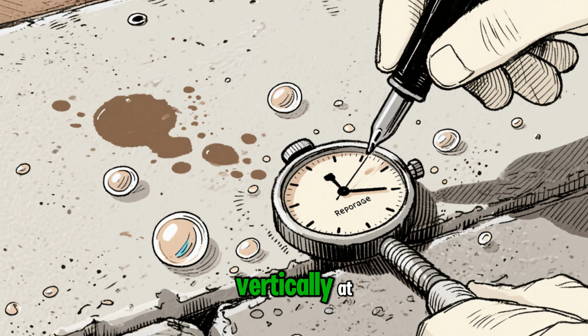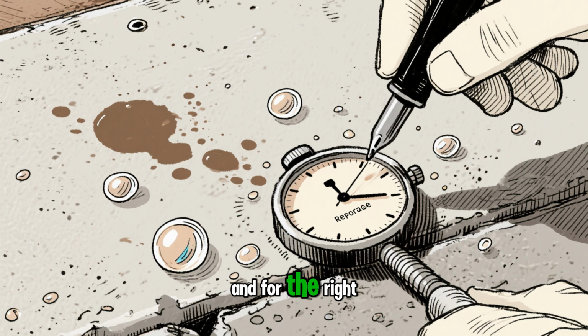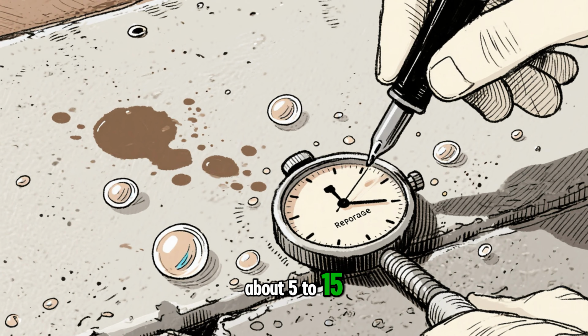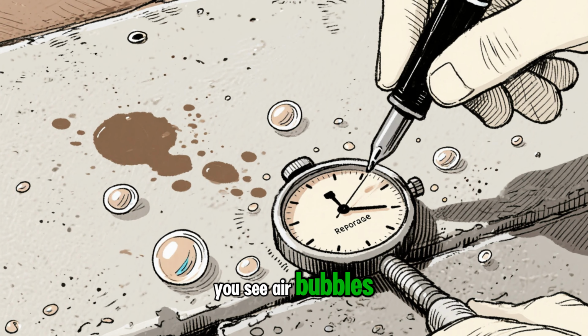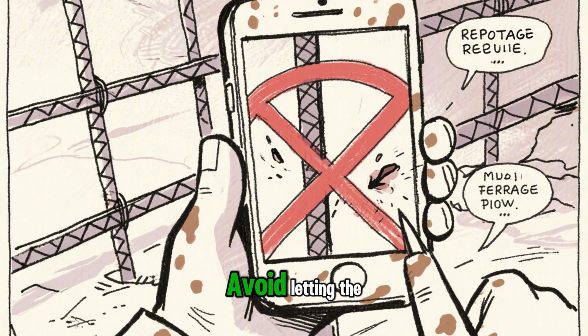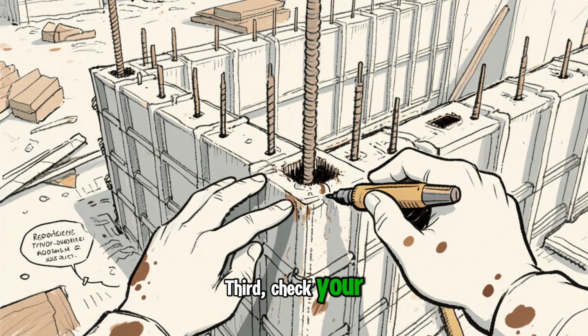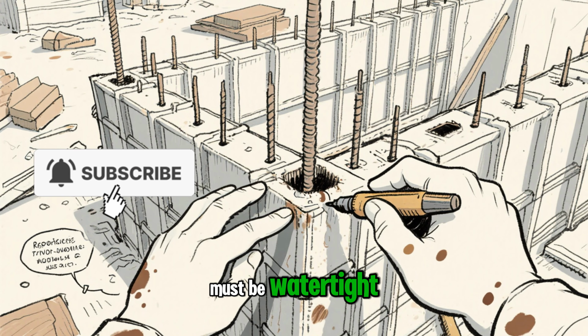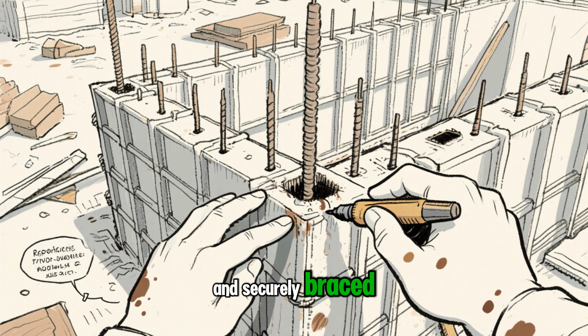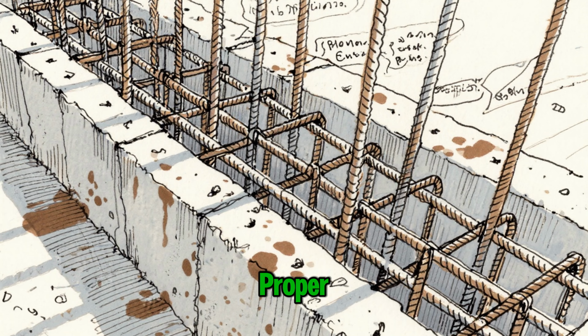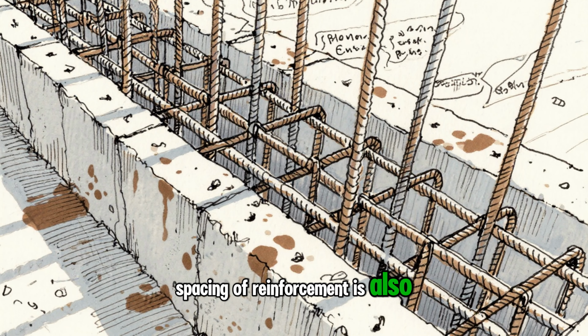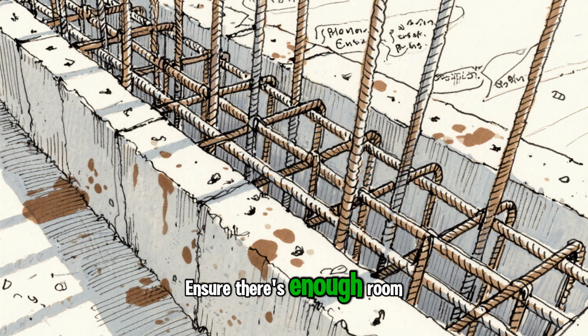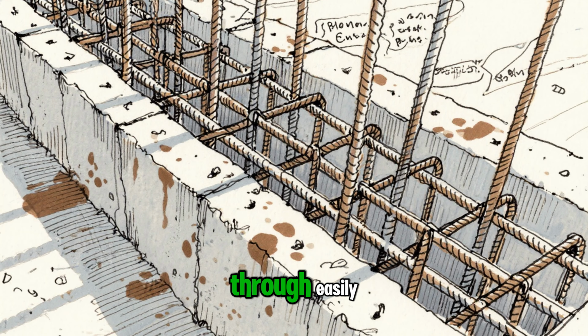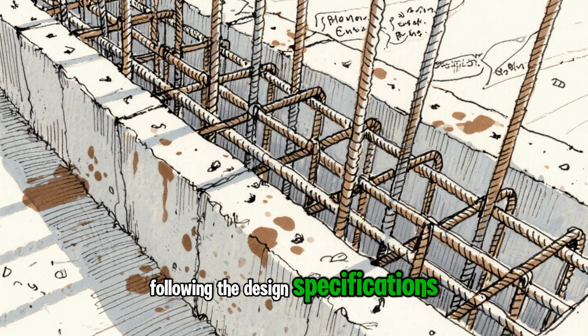Insert the vibrator vertically at regular intervals, and for the right duration, usually about 5 to 15 seconds, or until you see air bubbles stop rising to the surface. Avoid letting the vibrator touch the rebar or formwork. Third, check your formwork meticulously. It must be watertight and securely braced to prevent any grout leakage. Proper spacing of reinforcement is also critical. Ensure there's enough room between the bars for the concrete to pass through easily, following the design specifications.